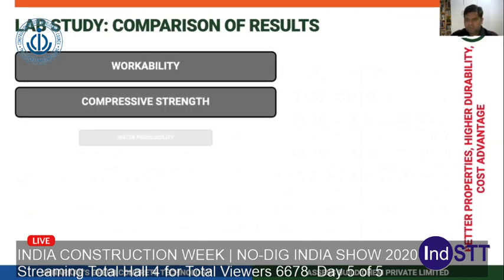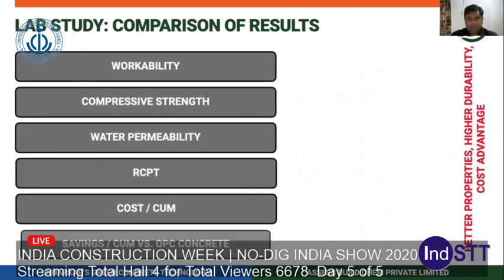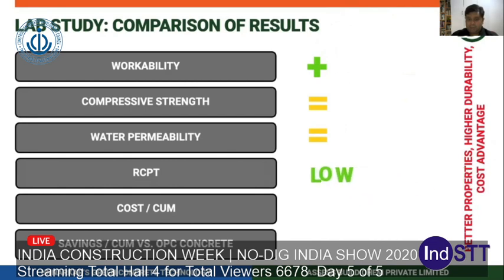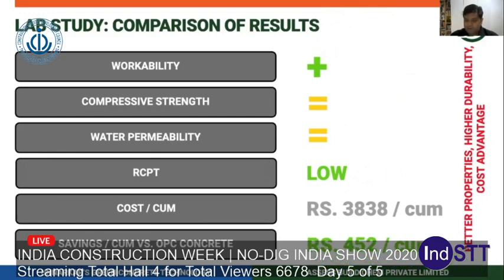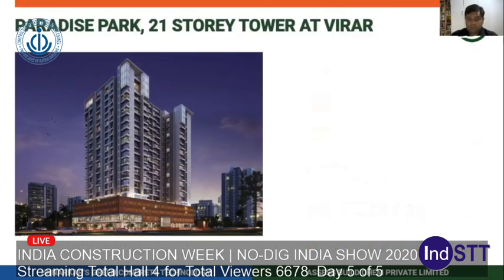I will not go much into the results themselves. But what we essentially saw was that even with the GGBFS mixes, the workability was much better as compared to OPC only. The compressive strength was very comparable. The water permeability values were very comparable. But what surprised us was that the RCPT values were much lower. That means the durability aspect of the concrete itself becomes much more interesting. The cost per cubic meter to batch on site was almost about 450 rupees cheaper as compared to a full OPC mix. And this kind of mix, we put it into practice.